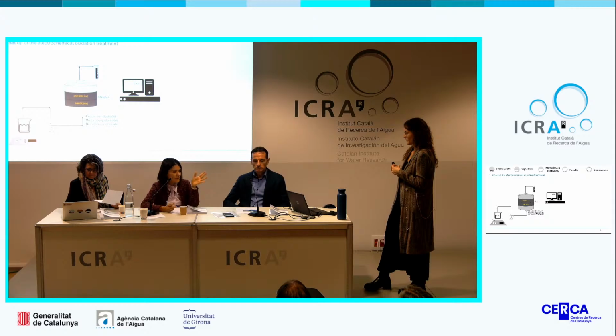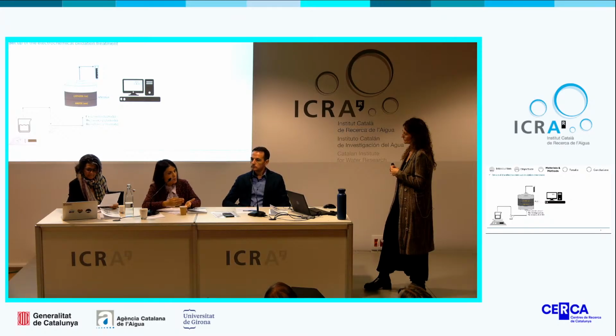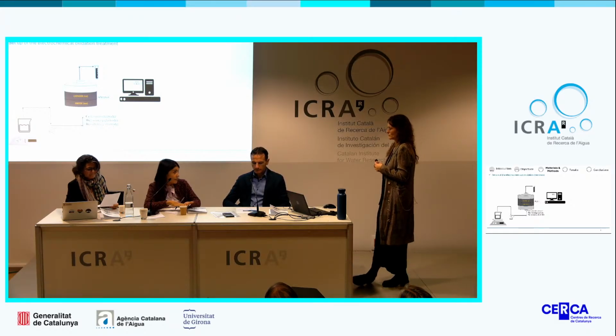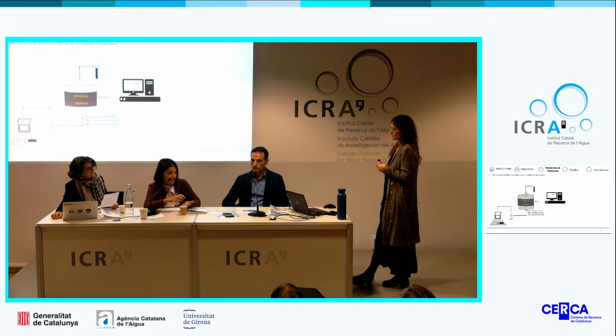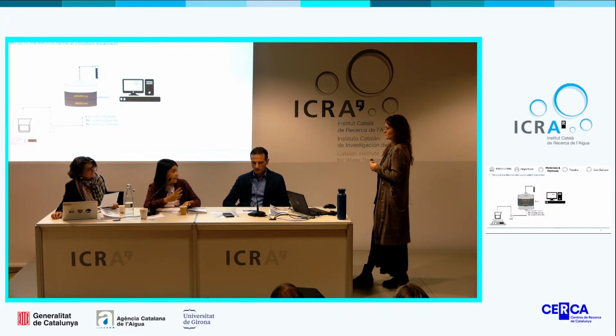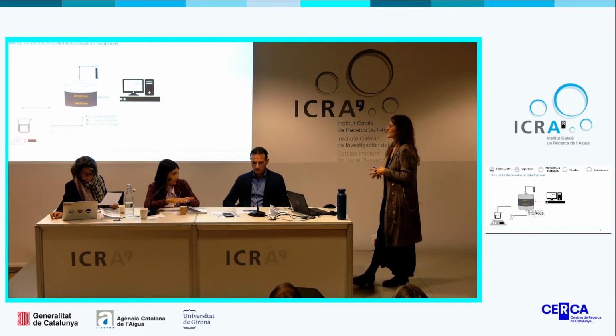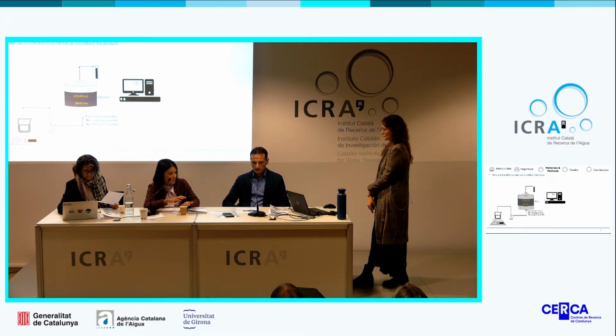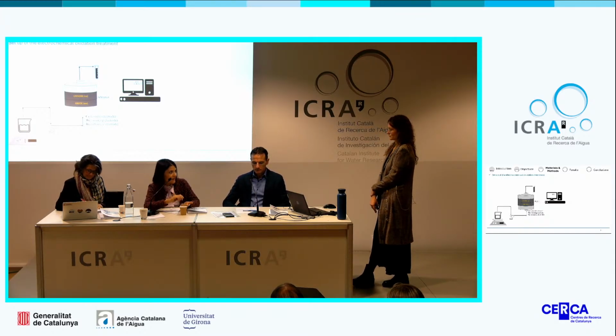My question is related to the main mechanisms involved in the degradation process. I don't know if it is the direct oxidation of the antibiotic on the electrode. In this case, you have to observe that the final products are different from the raw material retained on the electrode. Or if the main mechanism is the indirect oxidation by the ozone or the hydrogen peroxide produced in the cell.